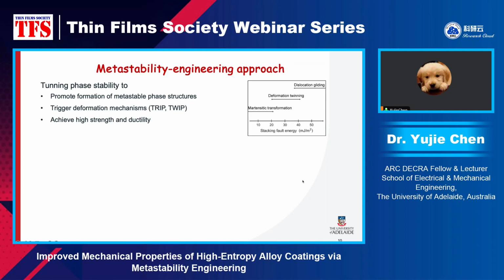Let's take an example. If we're working on an HCP or FCC structure, we know that stacking fault energy is very important, because all these deformation mechanisms are closely related to the stacking fault energy. If your material has a high stacking fault energy, the deformation will be mediated by dislocation gliding. If the stacking fault energy is very low, the phase transformation will occur. If you have something in between, deformation twinning will carry out the plasticity. So when we tune the phase stability, it's important that we pay attention to the stacking fault energy.